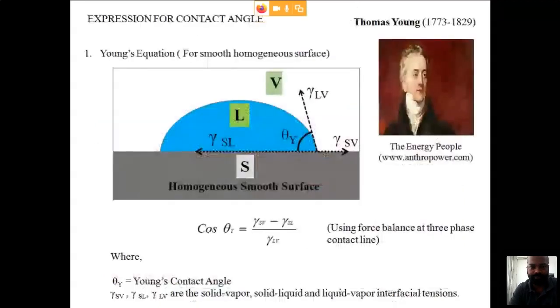But the contact angle concept in terms of a bubble is totally opposite. As I mentioned, the contact angle should always be measured through the denser medium. In the case of a bubble, the naming becomes difficult. That means a bubble on a hydrophilic surface actually looks like a hydrophobic droplet. So you have to be very careful when describing the contact angle related to a droplet as well as a bubble. But usually for convection, wherever the contact angle is measured, it is taken with respect to the droplet on the surface, and this analogy using the bubble is seldom used.